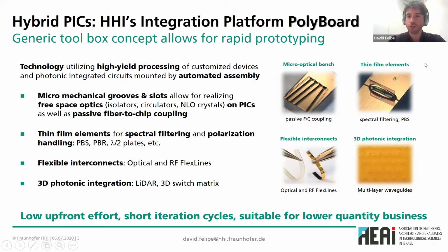Additionally, we can etch some slots on the polymer waveguides, as seen here on the top right-hand side, into which we can insert thin film elements, which might be designed for different functionalities, for example, for wavelength filtering or for polarization handling, in a very small footprint, as these filters are between 15 and 25 micrometers thick. We can implement a functionality which is non-temperature dependent due to the dielectric materials on which these thin film elements are fabricated.